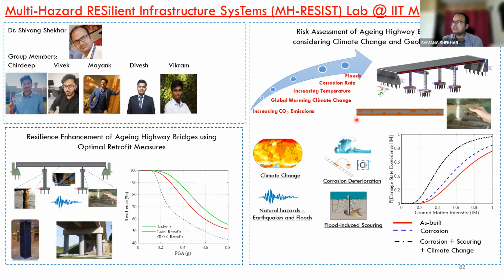And then we can model it by dividing my bridge pier into 100 mm small elements. For each 100 mm, we randomly pick a pitting factor and assign it. Then for the second 100 mm, we randomly pick the pitting factor and assign it. So in that sense, our results closely match the source from which we are taking the pitting factor.